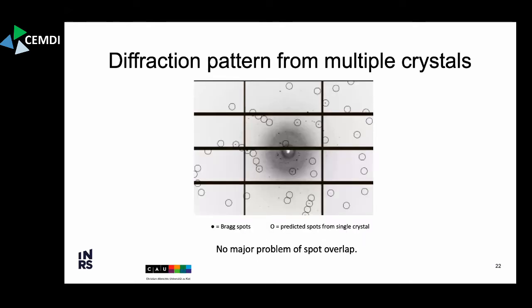Now I wanted to show what the diffraction pattern from multiple crystals kind of looks like, to argue that it's not a problem of the data. My argument is that it's a problem of the analysis that we currently have on hand in order to be able to expand the applicability of structure determination. You can see the circles here are the predicted spots from one single crystal, but you can see that there's a bunch of other Bragg spots in this diffraction pattern, but they're not overlapping, which means that the information is still reliable in those pixels. And so what we need now are algorithms that can identify what other crystals, what orientations and what other polymorphs these Bragg spots correspond to.